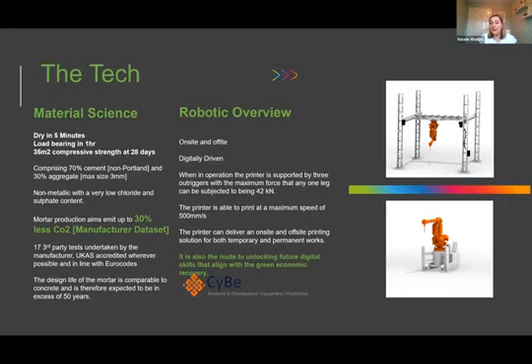The print speed itself, again, has to be quick because we've got a quick drying material. So you're looking at about 0.5 meters a second of it laying down. And again, you can see a little bit more about the fact that it's supported by 3 outriggers, and it can take a substantial force through one leg. So it has about a 3 meter print diameter in kind of a donut shape that when we're doing the digital design modeling, we would be constantly cross-referencing with, does this sit within the sphere of the print capability? And if it doesn't, it's not the end of the world. We just design to be more panelized or more modular, but where we can print to have one structure where we've got no joins, for example, then we're obviously playing to the strengths of the printer and the material.